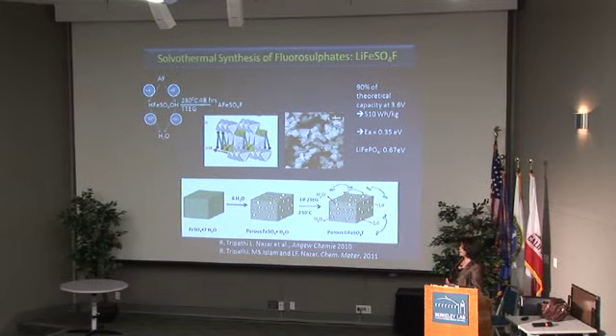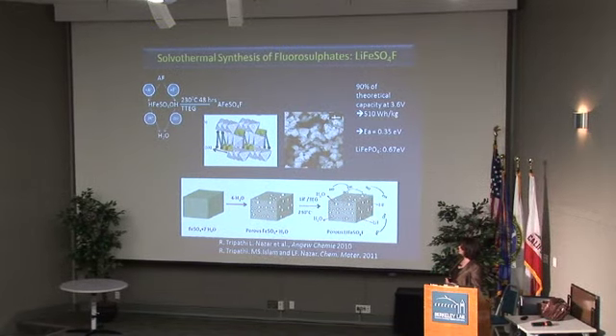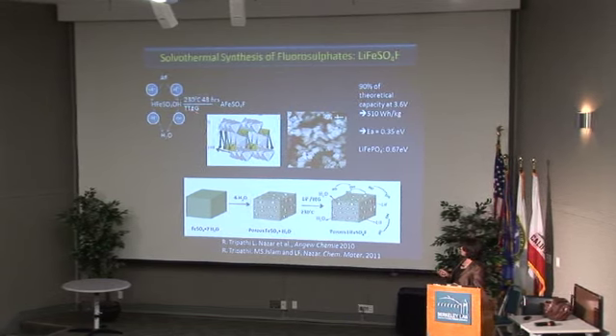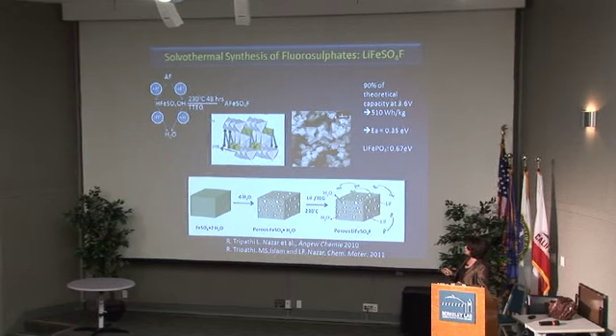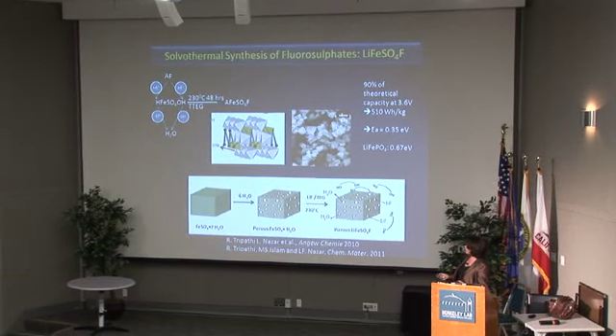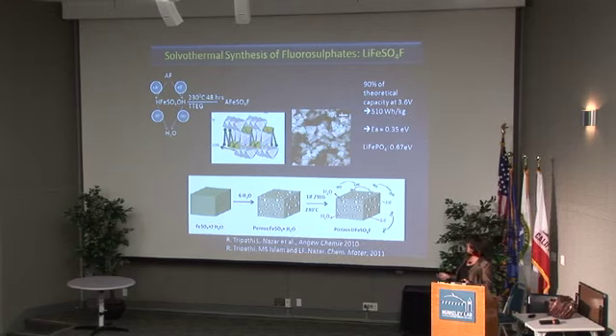This requires virtually no fussy, complicated carbon coating, and it's because it has a different structure, which is called a tavorite, which has three-dimensional ion diffusion rather than one-dimensional, such as the olivine. And in this particular case, we formed the material using just a glycol as our solvothermal reaction medium. And the reaction is probably easier seen here, and it is what we call a topotactic reaction.